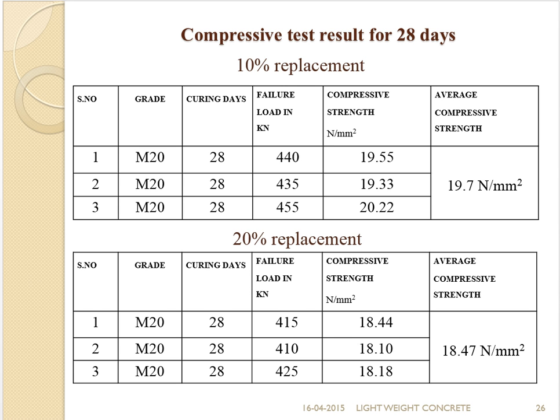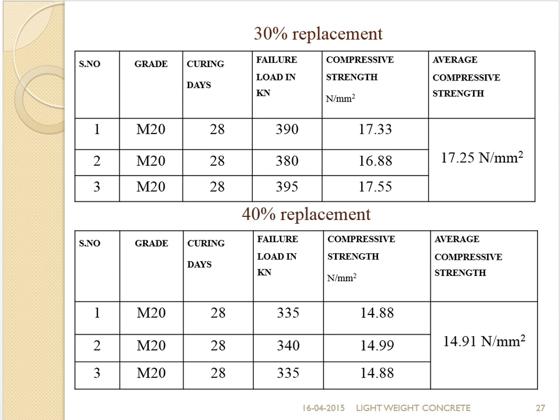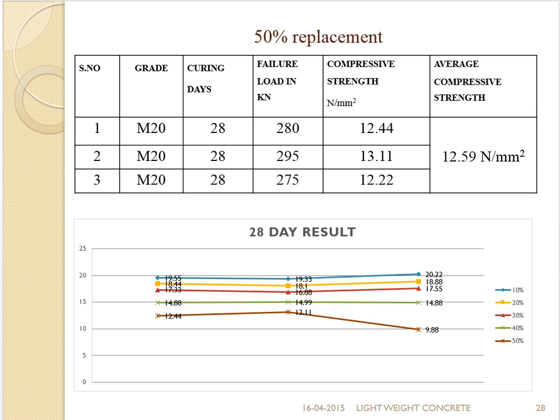And again, for the 28 days compressive test result, for 10%, it is 19.7 Newton per mm square. For 20, it is 18.47 Newton per mm square. For 30, it is 17.25. For 40, it is 14.91. For 50, it is 12.59 Newton per mm square, and the graph for the 28-day result is here.